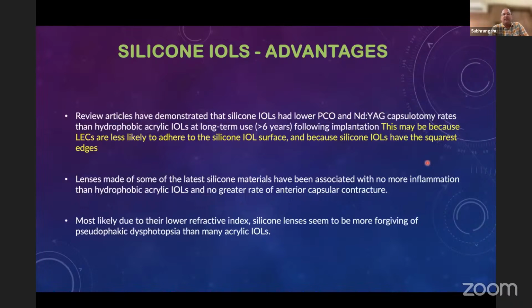Advantages: review articles have demonstrated that silicone IOLs have lower PCO and Nd:YAG capsulotomy rates than hydrophobic acrylic IOLs at long-term use following implantation. Secondly, lenses made of some of the latest silicone materials have been associated with no more inflammation than hydrophobic IOLs. And most likely due to a lower refractive index, silicone IOLs seem to be more forgiving of the pseudophakic dysphotopsias